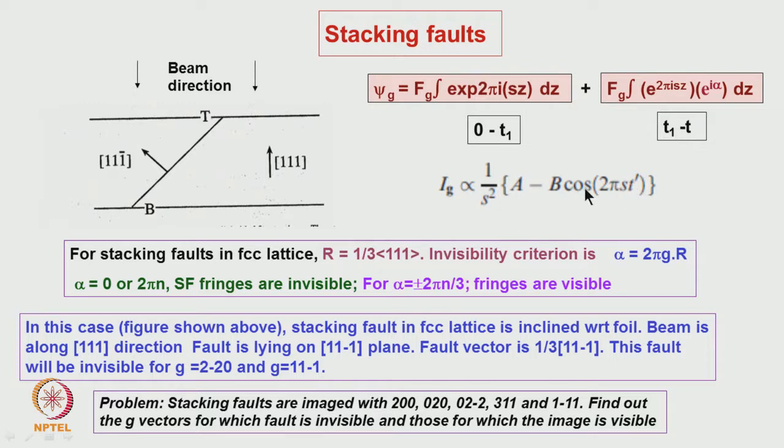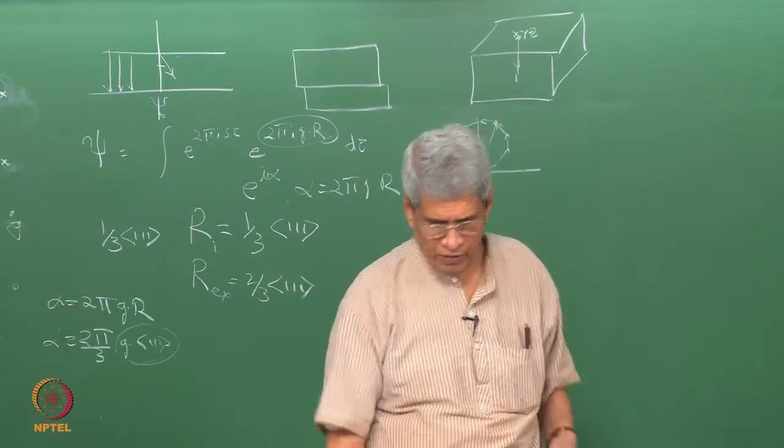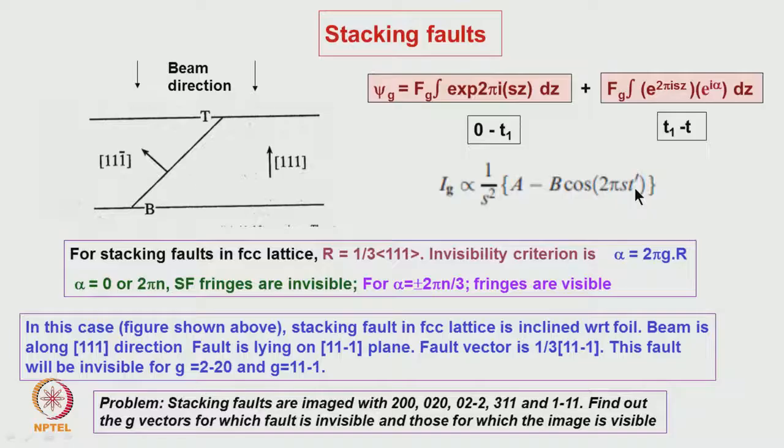And another thing is that it fluctuates with respect to s times t, which can take values such that the whole term becomes pi, 2 pi, and depending upon that the intensities will be fluctuating. So, when the intensity fluctuates as a function of t for a constant s, what we essentially get is a fringe contrast. This is exactly what is happening.